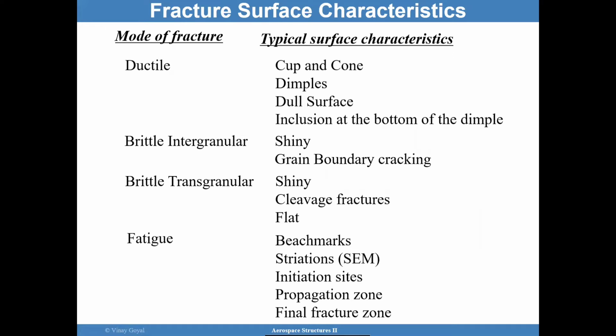You have ductile mode of fracture. The typical surface characteristics will include cup and cone, dimples, a dull surface, and inclusions at the bottom of the dimples. You could have a brittle intergranular mode of fracture, which is between the grains. So that's shiny; the grain boundary is cracking. You may have a brittle transgranular fracture, which is also shiny. You're going to have some cleavage fractures, and it's relatively flat. And then fatigue is going to typically have beach marks, striations, and initiation sites. You're going to have a propagation zone and a final fracture zone.